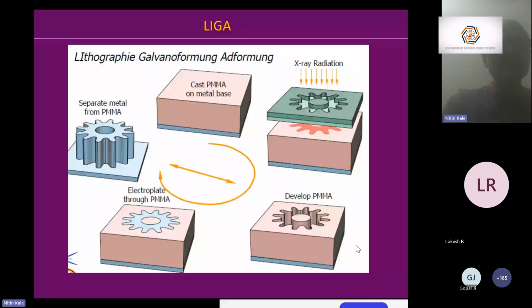LIGA is again a German term. It's a method to do X-ray lithography and make very thick structures. So what you do is, you have a metal base, you put some sort of an acrylic material like PMMA on it. Using a mask, you create your pattern of interest, you develop your material, then you electroplate. So this electroplating gives you a very thick material of your interest. You remove the PMMA and you have the thick material. So this could be, for example, a gear.